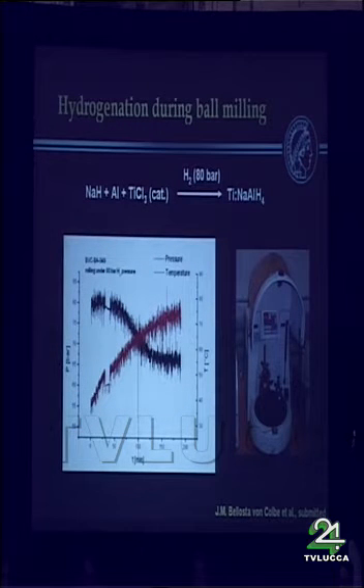I would consider this the most advanced method to prepare sodium alanate. We recently have developed a mill where we can, under about 100 to 130 bars hydrogen pressure, mill compounds and record temperature and pressure in the vessel by a radio transmission device, because you cannot attach cables to a vibrating mill tube. With this method, we start from sodium hydride, aluminum powder, and titanium trichloride in this case as the catalyst, pressurize it to 80 bars, and mill under the pressure. You see that after about 2 hours, this is the pressure curve here, hydrogenation of the material is complete, and we have a titanium-doped sodium alanate.